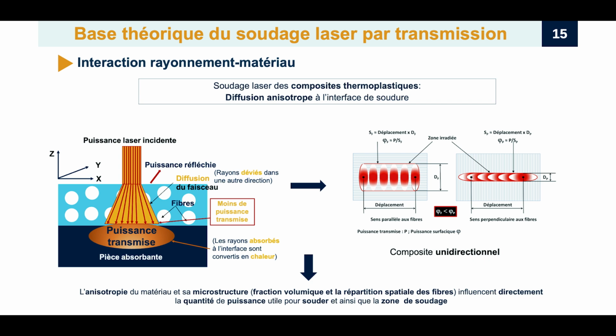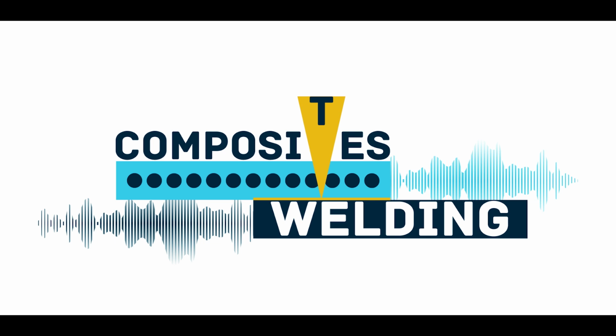It sounds like mastering this requires understanding the chemistry, the physics of heat flow, and the geometry of the material itself. And given how confined the heat is and how weirdly it can flow in composites, it really forces you onto that processing tightrope you mentioned earlier, which brings us to the absolute limits, the weldability window. Yeah, that's a perfect analogy. Creating a good laser weld in these materials is absolutely like walking a tightrope. There are two critical temperature thresholds, non-negotiable limits, and you have to stay balanced precisely between them. That narrow thermal zone is the processing sweet spot, the weldability window. Get it right, you get maximum strength. Get it wrong, you make expensive scrap, or worse, a part that fails in service.